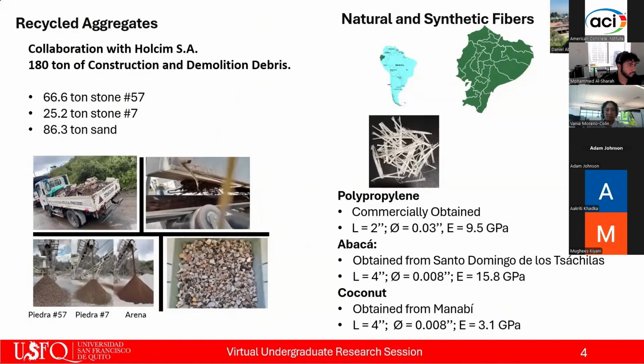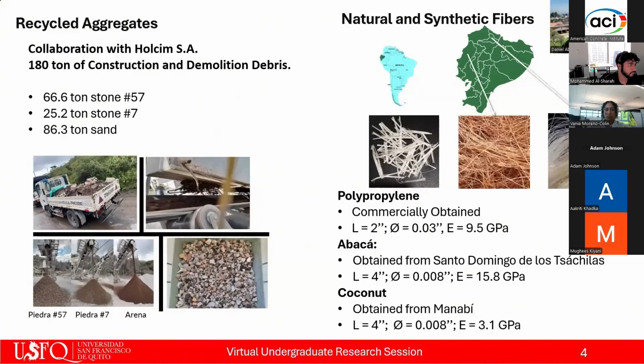For reinforcement, we used three fibers. Commercially available polypropylene fibers served as the synthetic control, with a length of 2 inches and a diameter of 0.03 inches. The natural fibers, abaca and coconut, were sourced from Ecuador, Santo Domingo and Manabí provinces respectively. Both natural fibers were 4 inches long with a diameter of 0.008 inches. The modulus of elasticity of the natural fibers was tested at the Materials Laboratory of Universidad San Francisco de Quito, with the results presented.